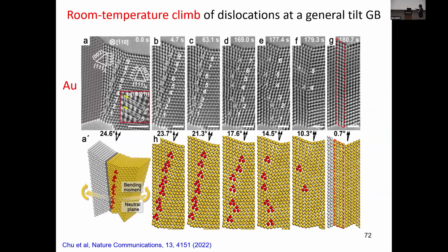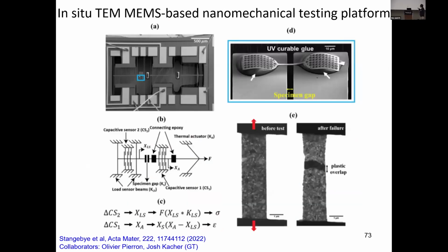So in this particular case, we can see that through also the in situ K2 camera experiment, we can capture many snapshots. So now we can directly visualize the climb of a grain boundary dislocation under mechanical load at room temperature. This is also quite unexpected, but if you think about the high stress playing the role of high temperature to promote the defect activity, it's now quite understandable.